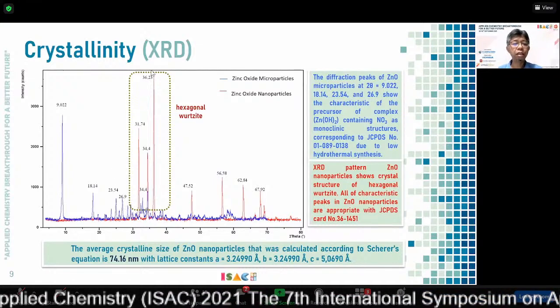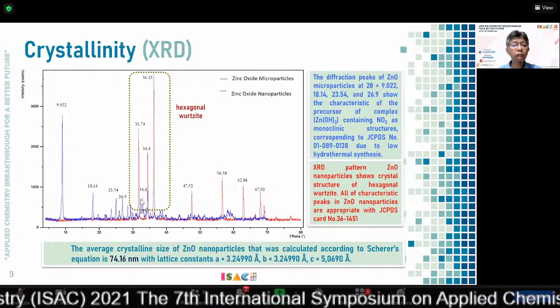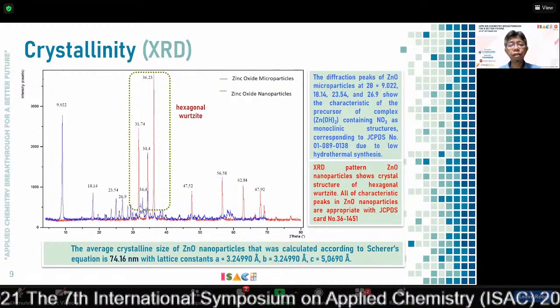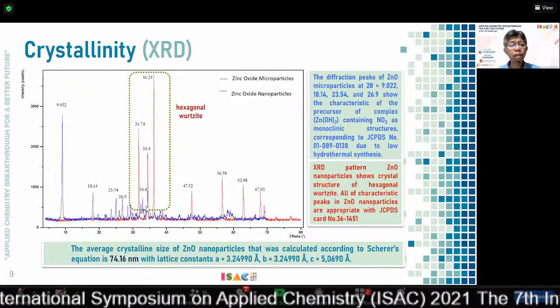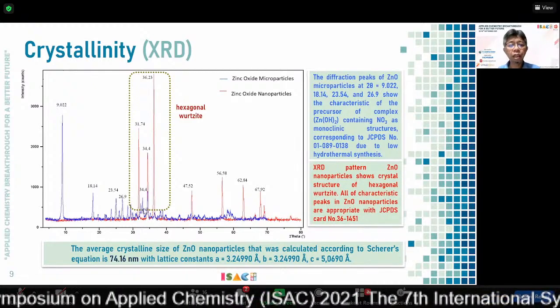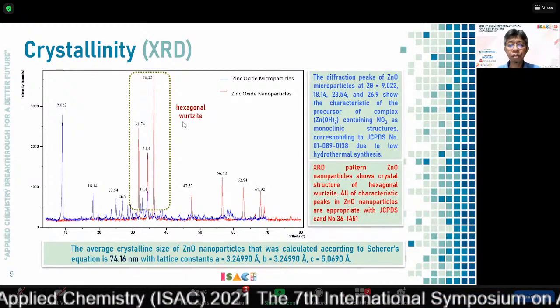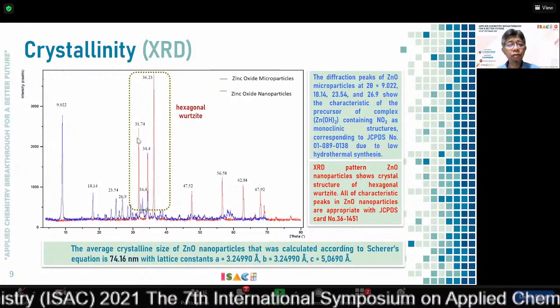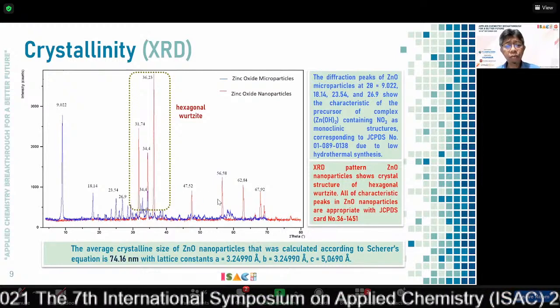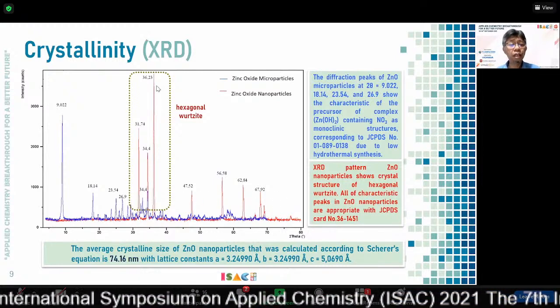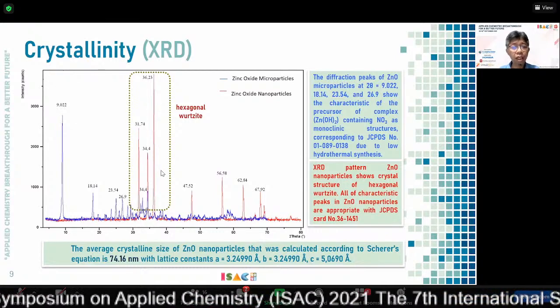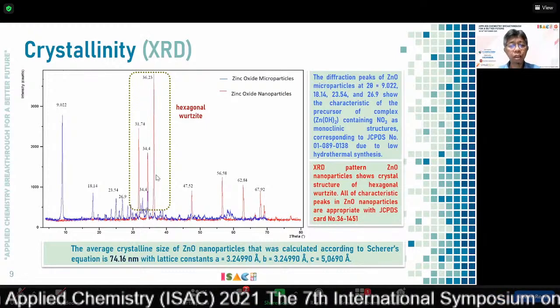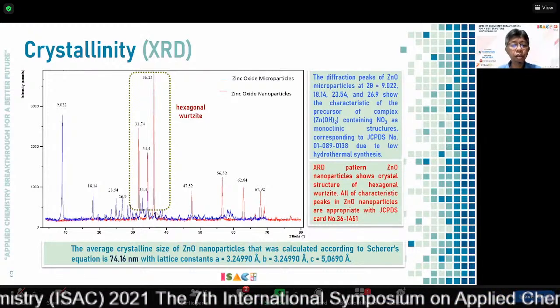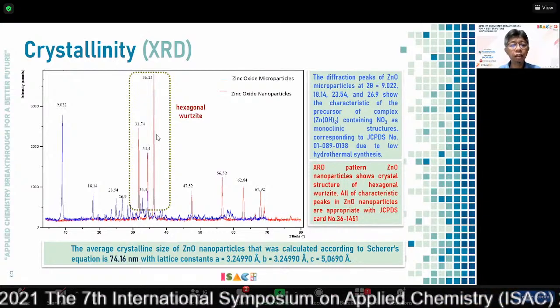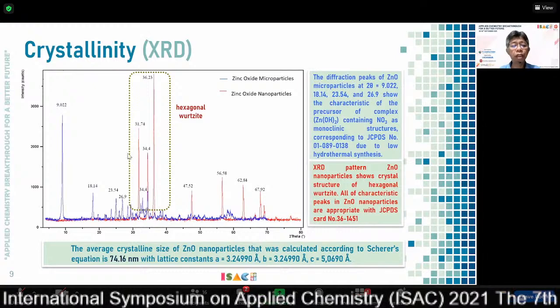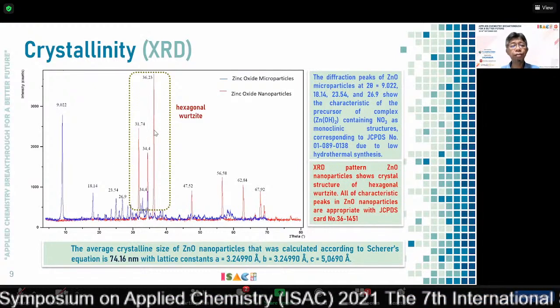105 degrees centigrade. On the other hand, for the zinc oxide nanoparticles, we can see that the pattern shows a crystal structure that, according to the JCPDS, belongs to the hexagonal wurtzite structure. And we can see that the peak is quite sharp here, which indicates a high crystallinity of zinc oxide nanoparticles. When we calculate by the Scherrer equation, we obtain an average crystallite size of zinc oxide nanoparticles of about 74 nanometers.